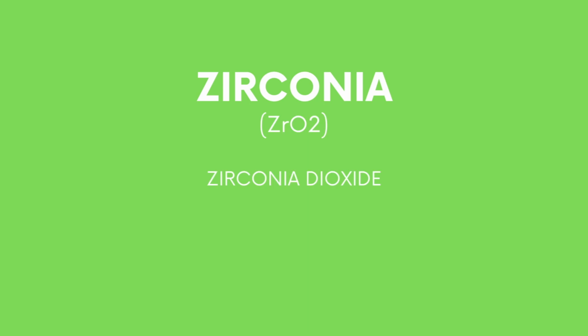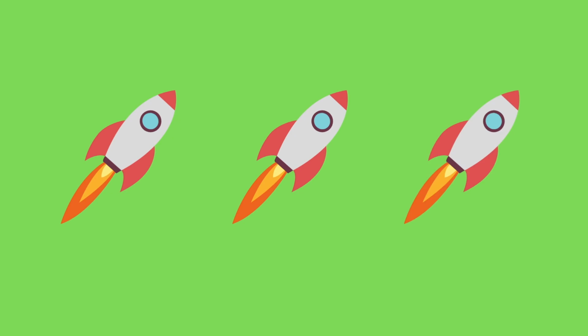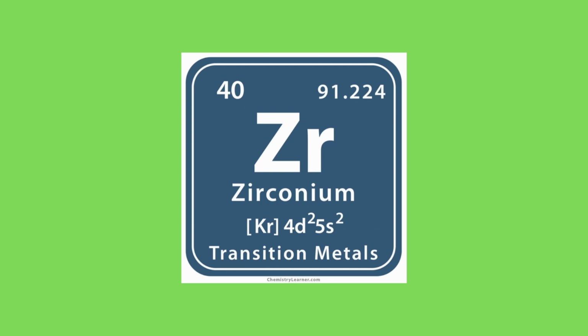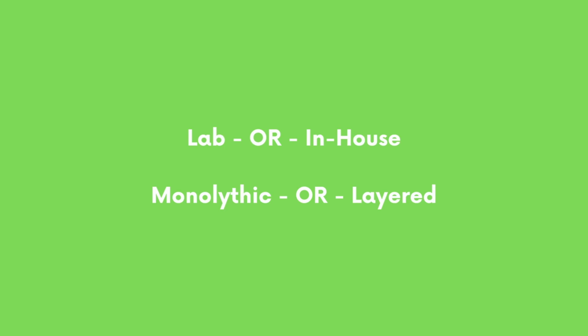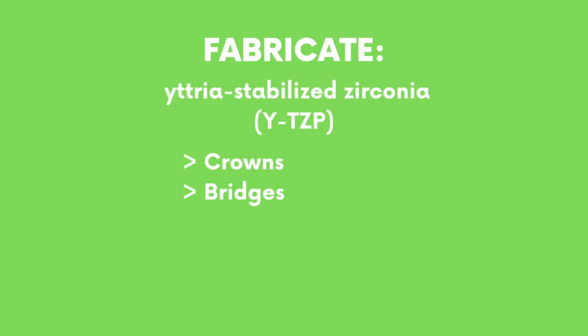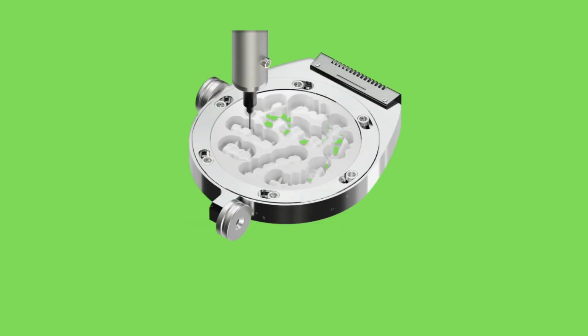This ceramic has become one of the most popular types of all ceramic restorations available today. It's actually derived from zirconium, the metal, but because of the oxidization and its formation into zirconium dioxide, it's considered a ceramic. It can be utilized in labs or in office through CAD/CAM technology for fabrication of copings, crowns, bridges, and implant abutments. Zirconia is milled dry in a green phase or a pre-sintered state and then sintered, during which the material shrinks about 20%.